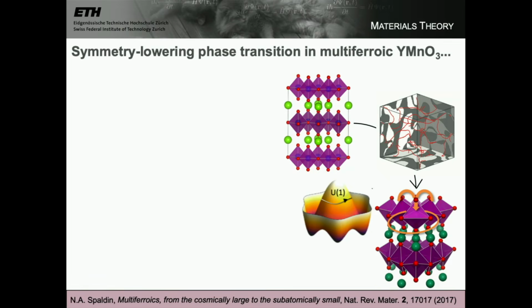In the case of our multiferroic yttrium manganite, we have a symmetry-lowering phase transition. It's a structural one, like the water to ice. In this case, from a high symmetry crystal structure, you see the yttriums are nice straight lines, and the MnO3 trigonally bipyramidally coordinated layers are nice straight lines. As we lower the temperature, there's a symmetry-lowering phase transition to this much more bent structure. And at the intersections between different bent regions, we form these lines, these intersections between the ferroelectric domains.